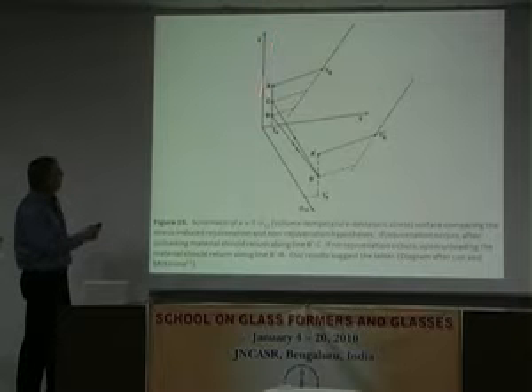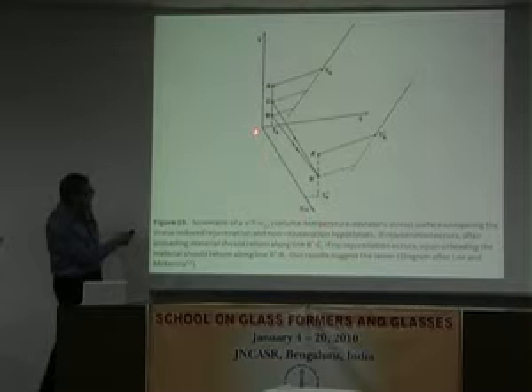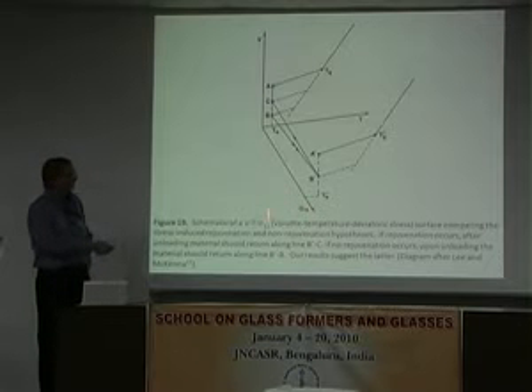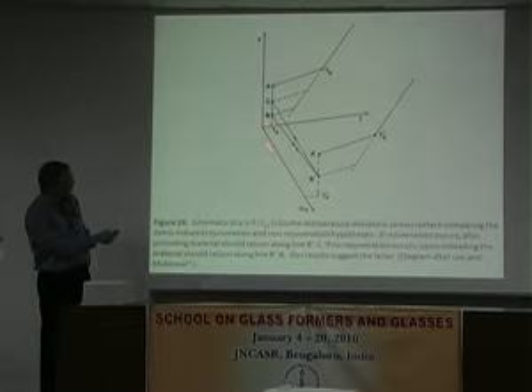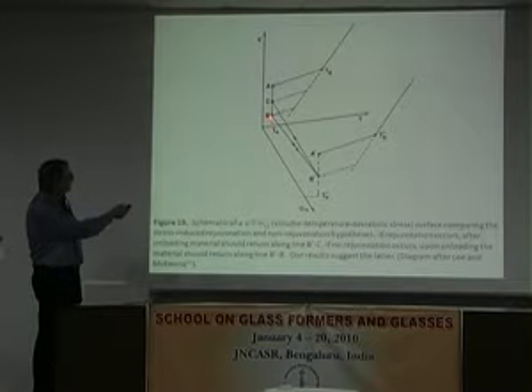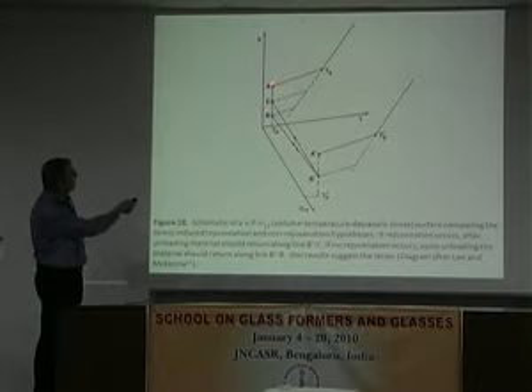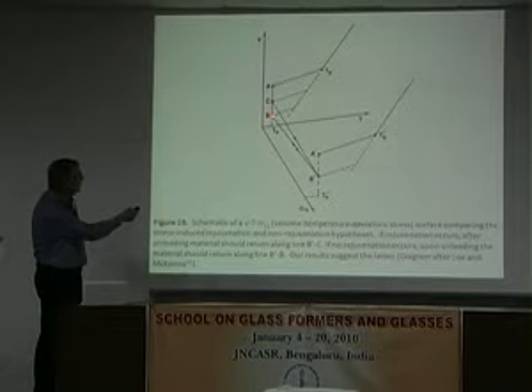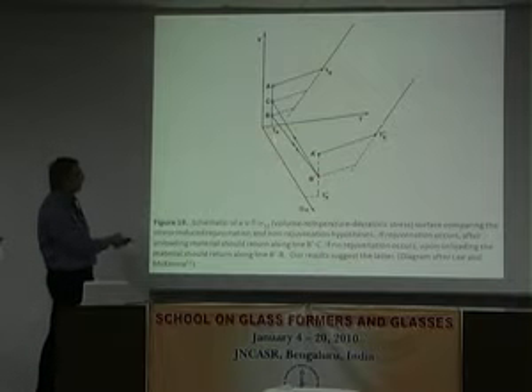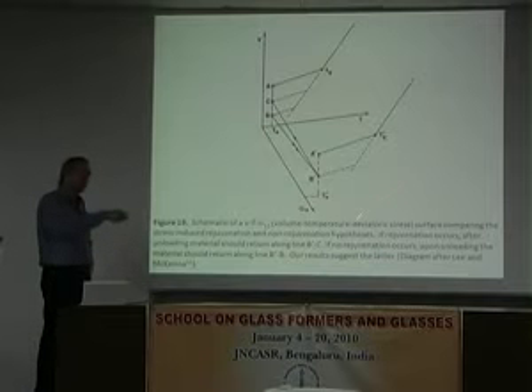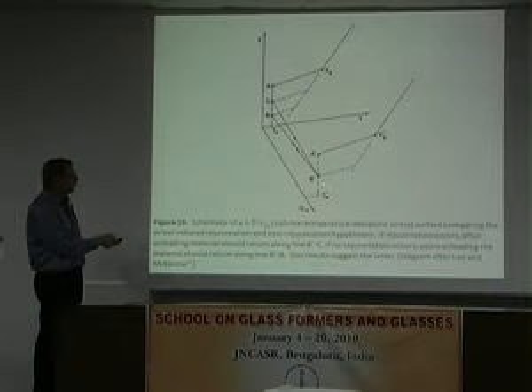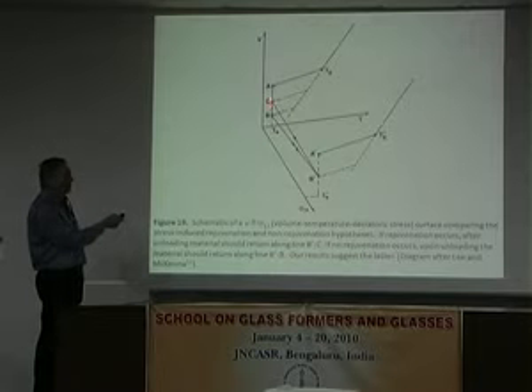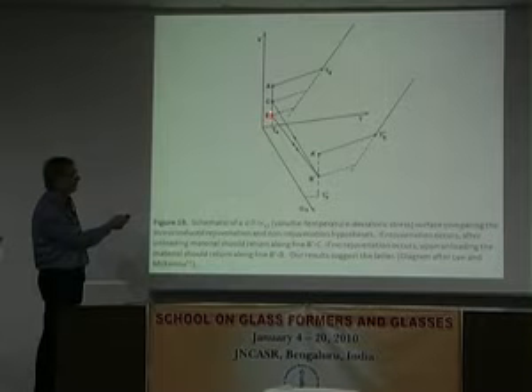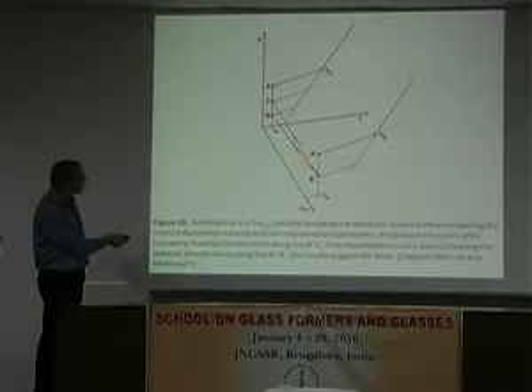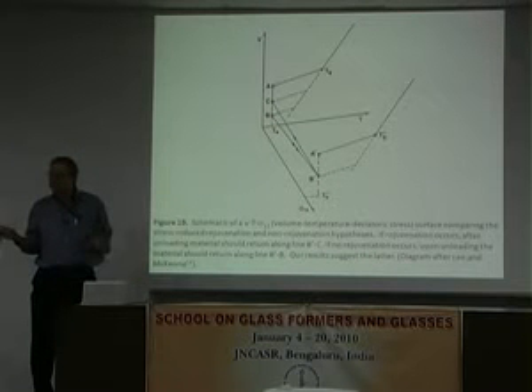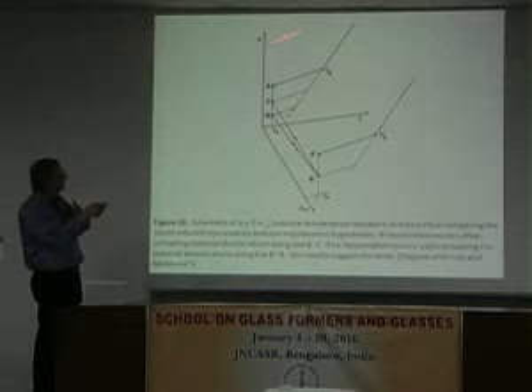So the rejuvenation hypothesis: if I imagine I'm on this volume-temperature plane, and then somewhere out here, some really complicated stress and stress history axis, it's really a mess, actually. But I chose to do it like it was elastic. What I'm going to do is quench in this plane, at 0 stress, and then let it age or recover down to point B. And then I put a big stress on it. Putting a big stress on it has a thermodynamics out here due to the stress. But the question is, whatever's going on out here, when I unload the sample, is it essentially going back to here where I've rejuvenated it, or is it essentially going back to here where I haven't rejuvenated it? Our interpretation is that it's essentially going back to here, meaning that what's going on out here is essentially decoupled from this.